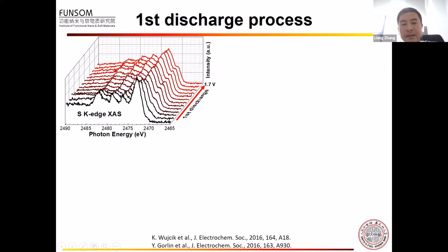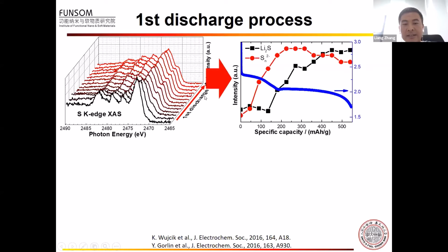We can see here the intensity of the main feature decreases during the discharge process. In addition, the pre-edge feature related to the polysulfide starts to appear, and it has the highest intensity in the intermediate discharge process. This is the intensity of the polysulfide and the lithium sulfide as a function of the capacity. We can see the intensity of the polysulfide increases rapidly at the beginning and then slightly decreases. This indicates sulfur is first converted to lithium polysulfide and then to lithium sulfide. This is also confirmed by the increase of the intensity of the lithium sulfide.